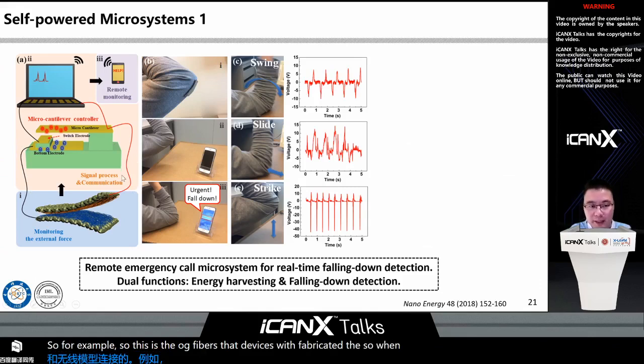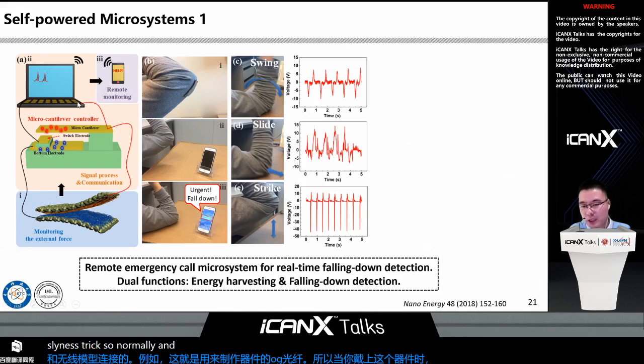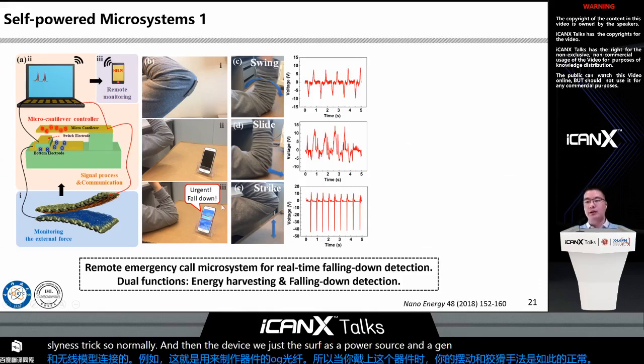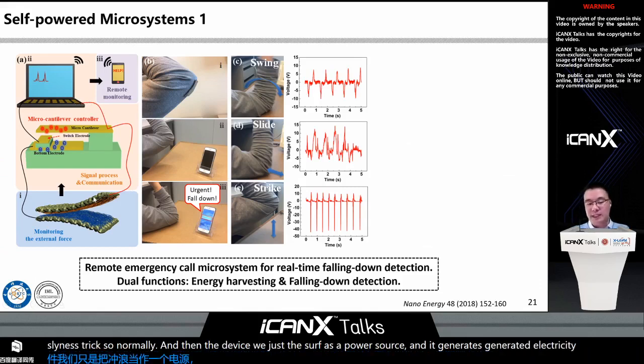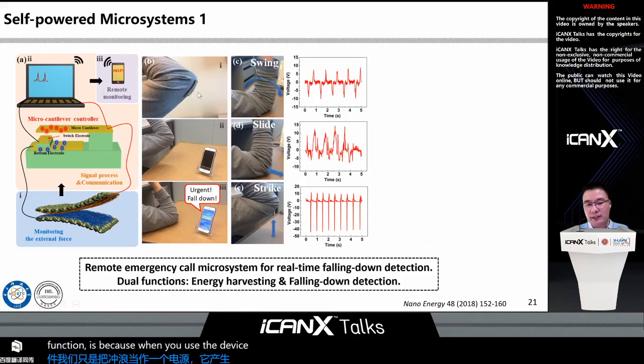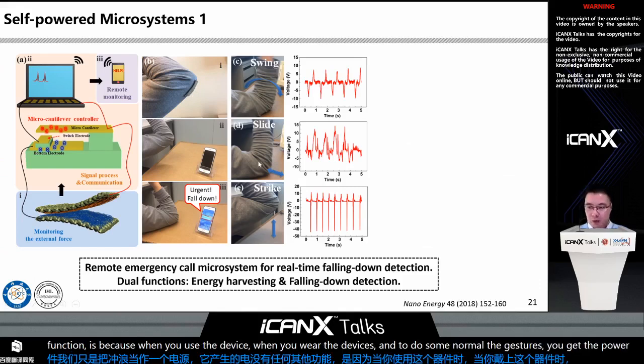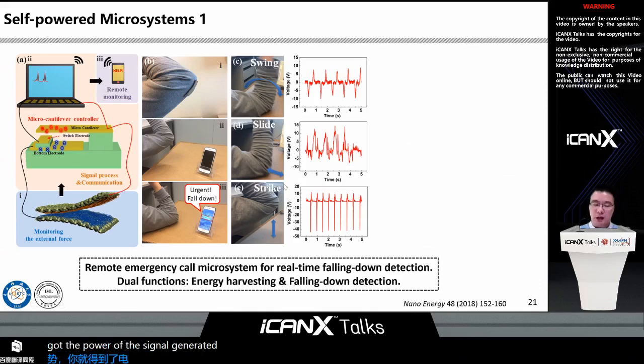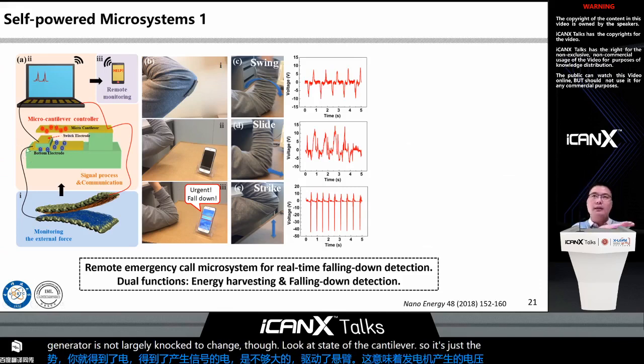For example, this is the all-fiber device we fabricated. When you wear this device and you swing, slide and strike, normally the device will just serve as a power source and generate electricity without any other functions. Because when you wear the device and do some normal gestures, you get power, but the signal generated is not large enough to actuate the cantilever. It means that the voltage generated by the nanogenerator is not large enough to change the working state of the cantilever, so it just stays in the off state.